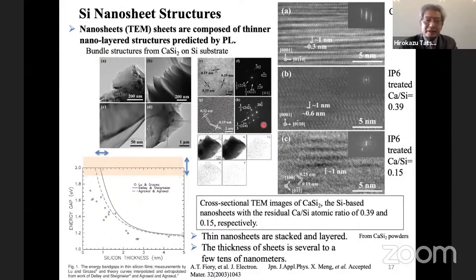And for the cross-sectional view, it is interesting that the original calcium silicide structure remains even after calcium is extracted. So this is the original CaSi2 template. Even though the calcium atoms are extracted, such a layered structure still remains. So please keep in mind that about 1 nanometer periodic structures still remain along the C-axis.